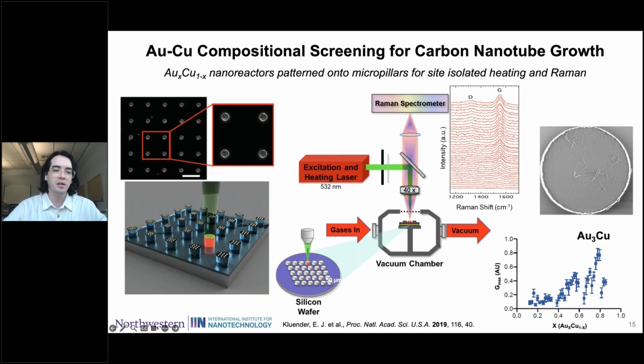And so what we did is we made a gold copper megalibrary on top of these pillars on a surface. The reason we're using these pillars is that we can shine each one individually with a laser, so that we can heat each pillar up to 600-700 degrees in complete isolation from adjacent nanoparticles. And then at the same time, use Raman spectroscopy to quantify the extent of carbon nanotube formation on each pillar.